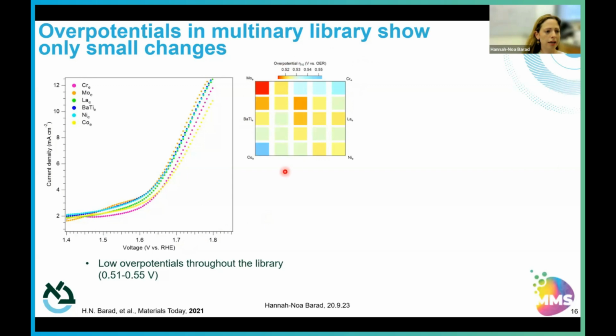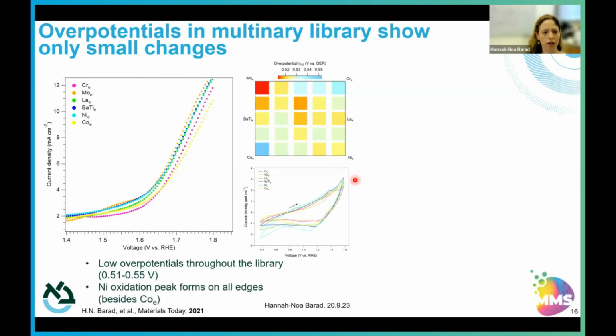And we get pretty much, I mean, this is just 25 points along the library that I plotted here, but we pretty much get similar overpotentials throughout. And after really investigating this in depth and trying to figure out if we were having issues with the reference electrode, well, it actually turned out that if we looked at the CVs, the most active material seemingly was nickel. So each and every one of these peaks is associated with oxidation of nickel.